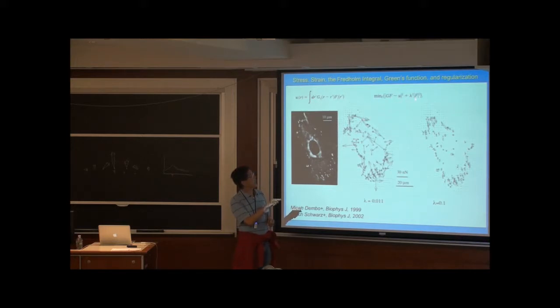What I do is I add to this, I want to not just minimize that, because then I'll just have a complex force field. I'm going to add this penalty term. And the penalty term is how complex is the force field. So this is just lambda squared F squared, right? So all I'm doing is I'm putting a penalty in for having a very complex force field. If this force field gets very complicated, I'm going to say that's not good. That means that I'm sort of overcomplicating the solution.